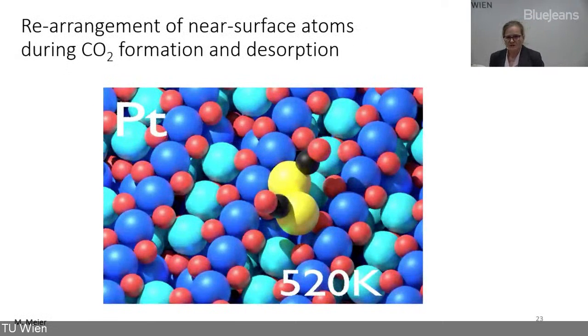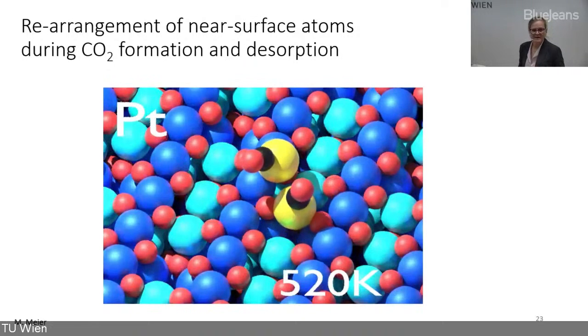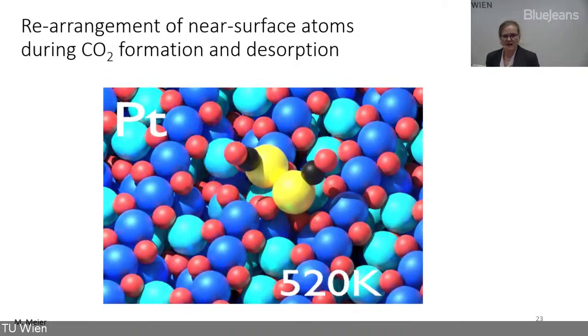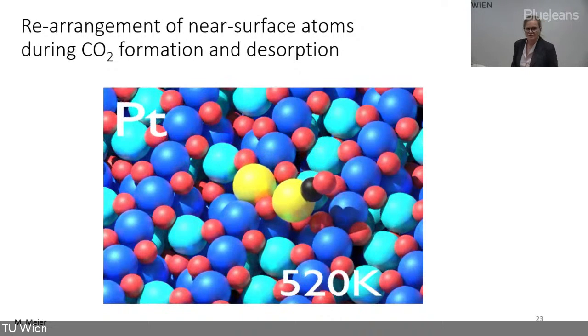Because we know so well how these CO dimers sit on the surface, we can also model how they react and how, when it desorbs, it takes an oxygen atom off the lattice. This is work from Matthias Meier, who tried to model this process with density functional theory from first principles, using all the information we gave him from experiment. This is what he came up with: here's the CO dimer, and one of the CO molecules catches oxygen from the substrate and desorbs it as carbon dioxide.